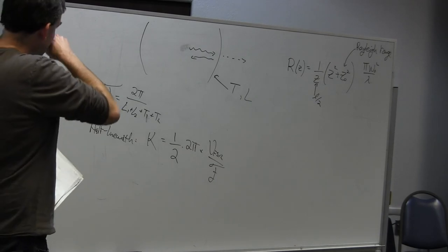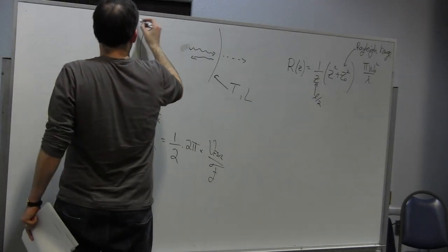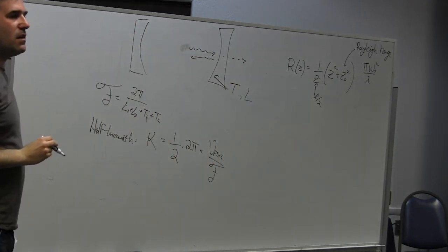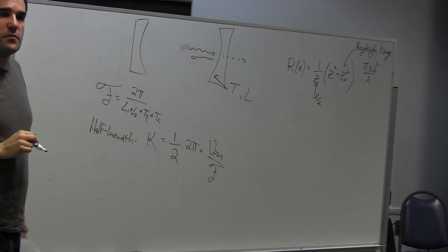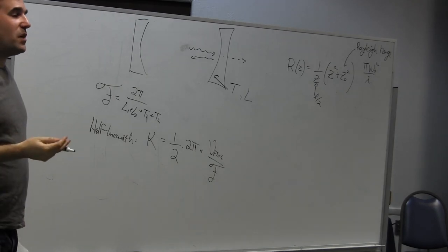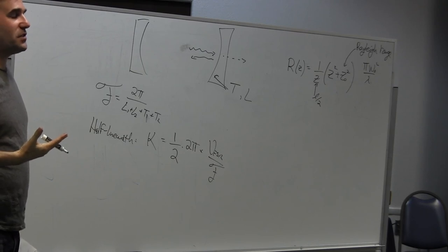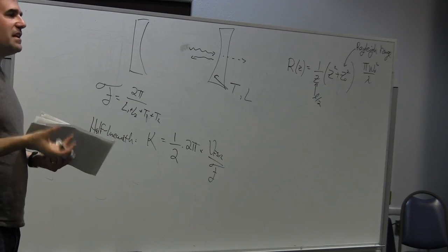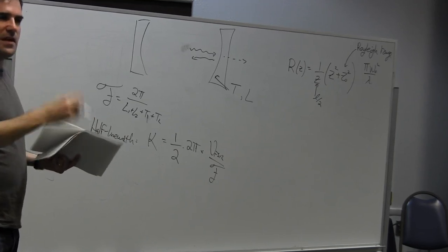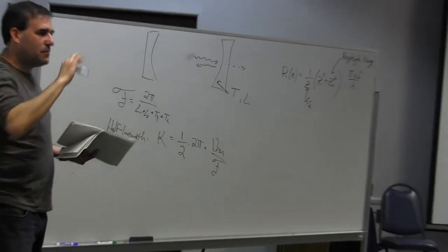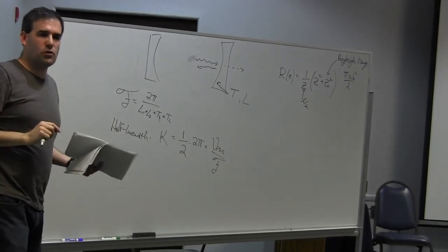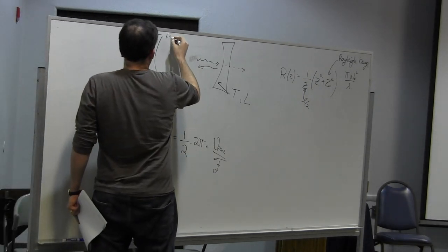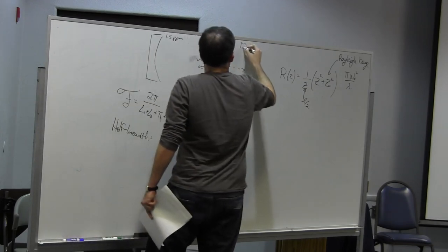And let me give you a real life example. So I have these two mirrors. And when I built the cavity, I wanted to make sure that most of the light would escape from one of the mirrors and not from the other. But unfortunately, I had bought two mirrors, which both had really great reflectivity, very low transmission. What was I to do? Well, I handed it over to my grad student. And he dips it in an acid, and then in another acid, and then back in the first acid, then back in the other acid, back and forth, peels off a bunch of these dielectric layers, and now we have a more transmissive mirror. Great idea. Okay, so now one of them has a transmission of 1.5 parts per million. The other one has a transmission of maybe 12 parts.